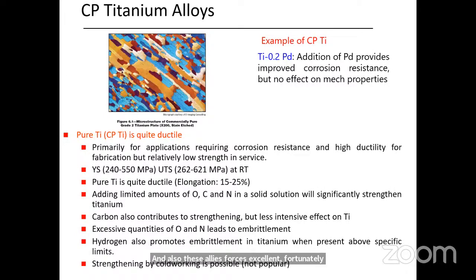So this is the CP titanium microstructure. You can see this is commercially pure titanium, a grade 2 titanium plate. You can see very fine equiaxed grains in this. These alloys sometimes intentionally have 0.2% palladium added for improving the corrosion resistance. Generally CP titanium is quite ductile. These alloys are mainly used in chemical plants. These alloys possess yield strength in the range of 240 to 550 and UTS in the range of 260 to 621. Pure titanium is quite ductile and you will get elongation of 15 to 25%.